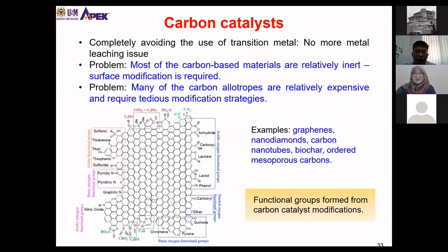And another problem is that carbon allotropes, right? Let's say you have graphene, nanodiamonds, carbon nanotubes. They are very expensive. Okay? They are quite expensive in the sense that if you look at single wall carbon nanotubes, it can cost up to about 2,000 ringgit per gram. Okay? It's so expensive that it's not sustainable to use this as a catalyst for our application. And we did some innovation to solve the inertness of the carbon-based materials and also to look into how we can reduce the cost of carbon-based catalysts.